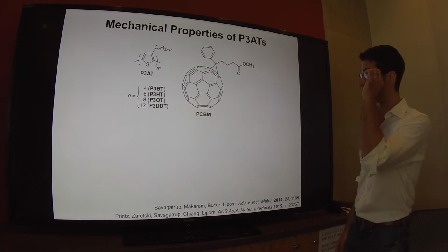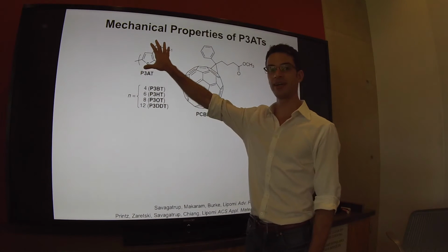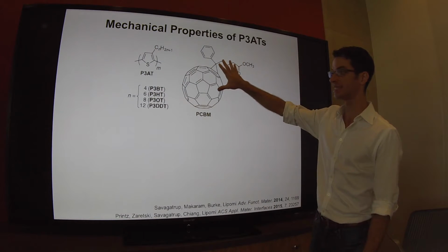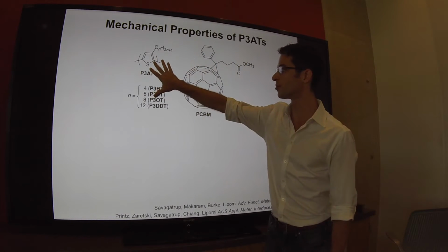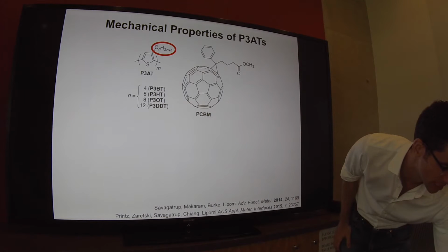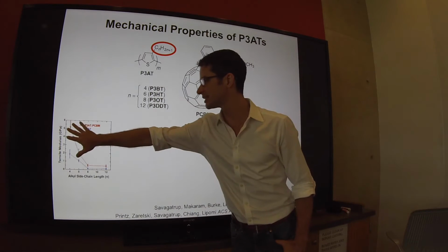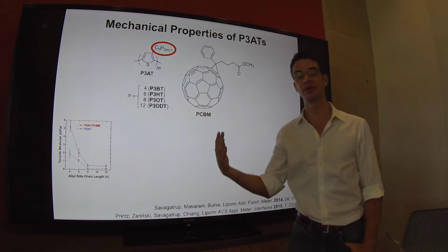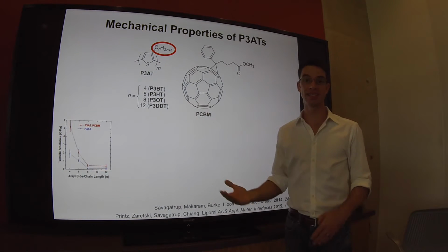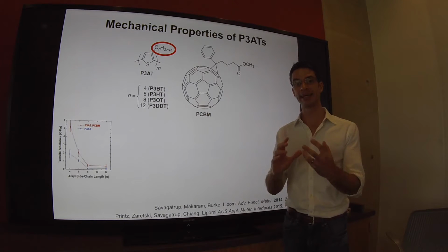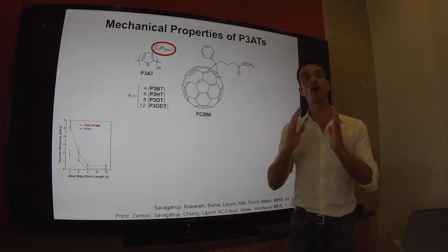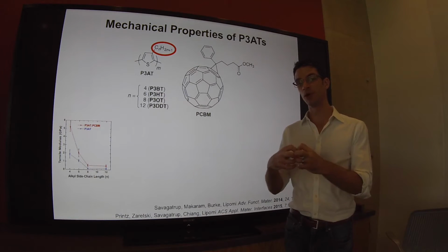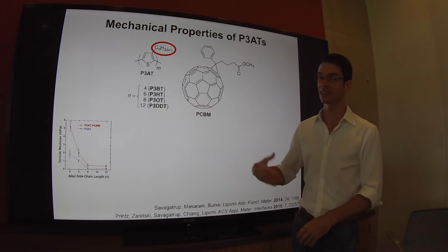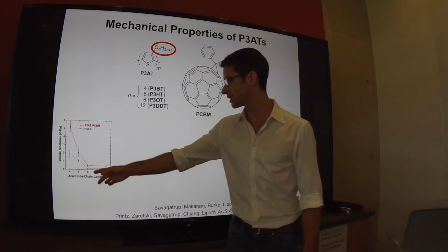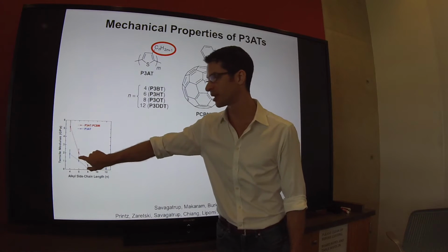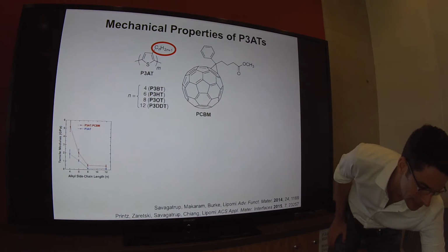Let's look at some of the molecular effects. In particular, if we look at just the poly-3-alkylthiophene and the C60 PCBM, in both the neat form and the blend with the two materials, and we look at just the function of the alkyl side chain length, we see that the tensile modulus goes down with increasing side chain length. We can rationalize this observation just by considering the fact that the longer the alkyl side chain length, the lower the density of load-bearing carbon-carbon bonds along the strained axis, so that makes the material more compliant. If you look in particular, there's a big difference between C6 and C8. There's about an order of magnitude difference represented here, and we'll get back to that in a moment.